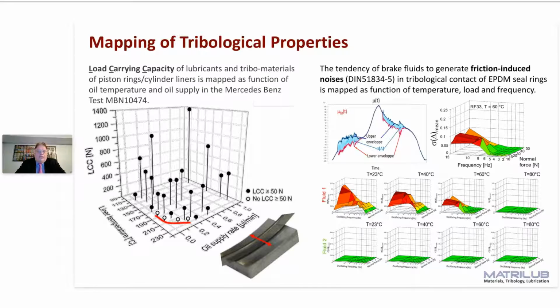The same, maybe a little bit easier to understand, is on the right side: friction-induced noises of EPDM seal rings and brake fluids. The point is, when a brake fluid makes noise, then you get oscillations in your friction signal. And these oscillations are shown here in light blue. And the area of this surface is the quantity you report as sigma delta. So let's have a look. You see in these tests, you change the frequency, you change the normal force, and you test at different temperatures.